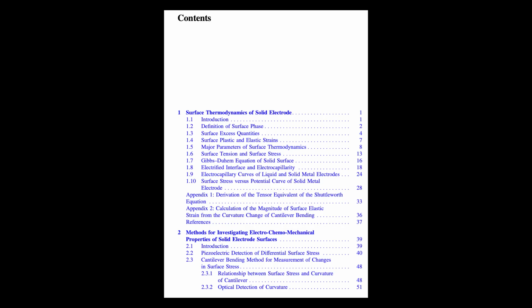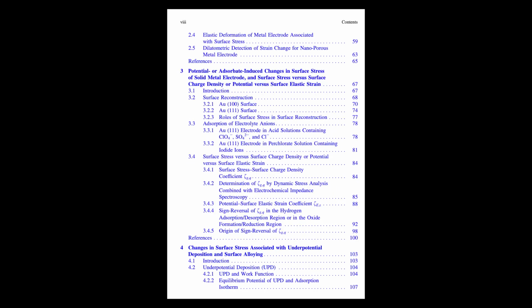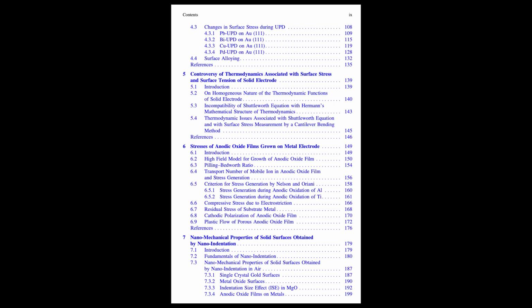So it's not just the metal atoms, but everything in that electrochemical environment that can tweak these surface forces. Absolutely. And even just the mismatch in the size of the crystal lattices between the deposited metal and the substrate, like with palladium on gold 111, contributes to the stress too. Although sometimes the theoretical calculations based just on lattice mismatch don't perfectly match the experiments, which tells us other factors are still playing a role we need to understand better. These UPD examples really drive home how intricate this all is. The electrochemistry and the mechanics are completely intertwined at the atomic level.